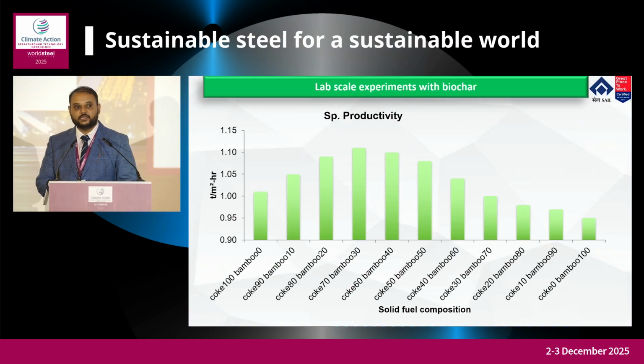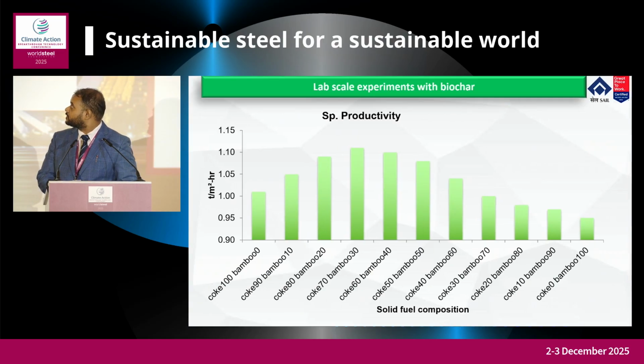First of all, we have tried from 0% to 100% utilization ratio, with replacement at 10% intervals. As we can see, the productivity is at a peak level at around 30 to 40% replacement, beyond which the productivity gets reduced because of strength deterioration and breakage tendencies.